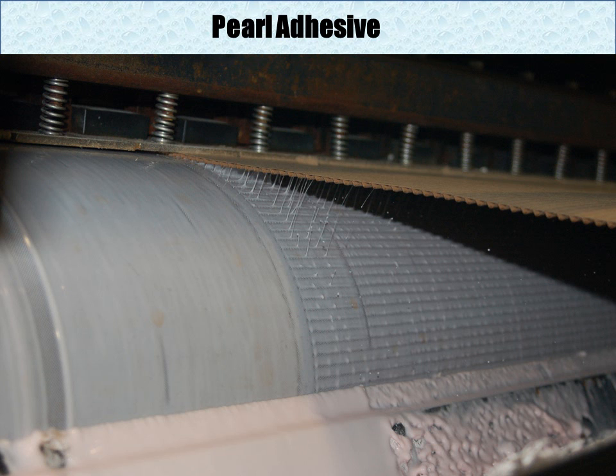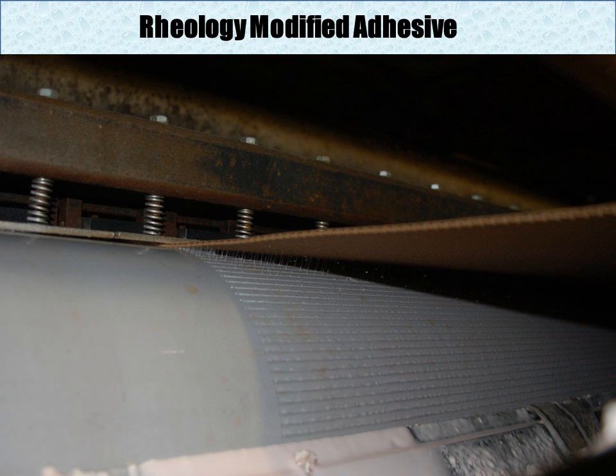Look at how sloppy typical pearl starch on a traditional glue machine performs. Look at all the slinging going on, all the number of uneven areas where the starch has not flowed correctly on the roll. This is a typical starch formulation without Fast Break rheology modifier. Think about how much starch is not being picked up by the flute tip. Now, look at the same machine, same speed, with the Fast Break rheology modified starch. You can now see limited or no slinging. The flow of the starch film on the glue roll is much more even, which results in a higher flute tip transfer rate, thus giving a better bond.